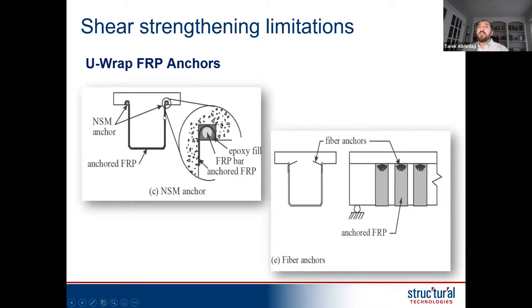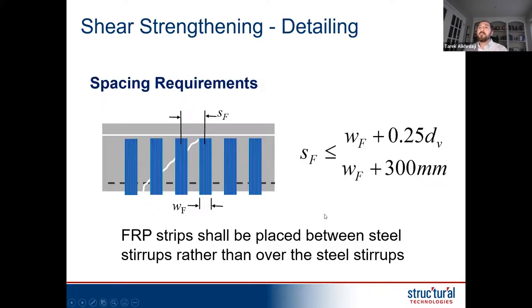Other thing is that this reinforcement for shear can be anchored. It can be anchored with FRP bar or with these anchors that I showed you at the beginning, the fiber anchor where you drill in and splay the FRP. And if you do that, then you can utilize higher contribution from the FRP based on the current standards.